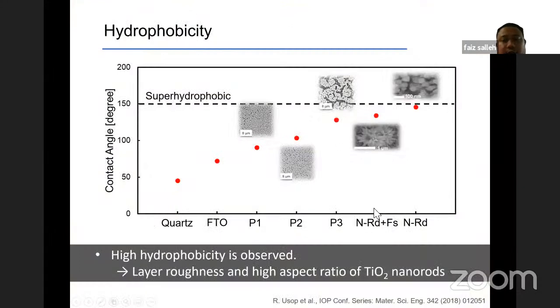Also, the bilayer contains nanorod and nanoflower, and there is the single layer with nanorod only. So we can see that we can improve the hydrophobicity of the TiO2 layer. And we can see here that the single nanorod layer has the highest hydrophobicity, or contact angle, near to the super hydrophobic ability. This is likely due to the layer roughness and high aspect ratio of the TiO2 nanorod.